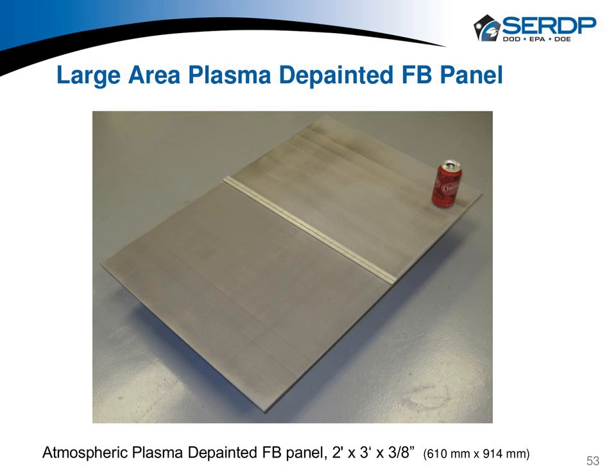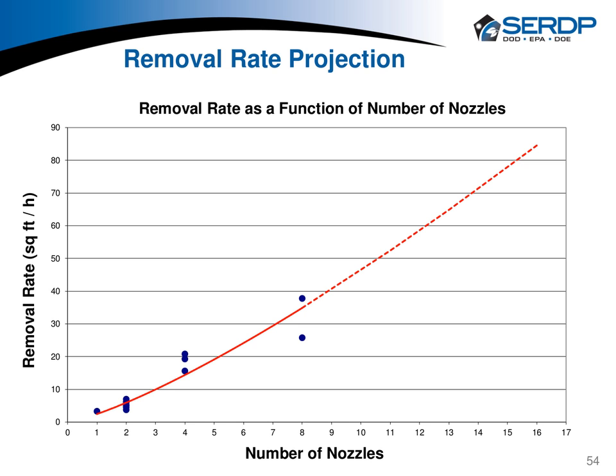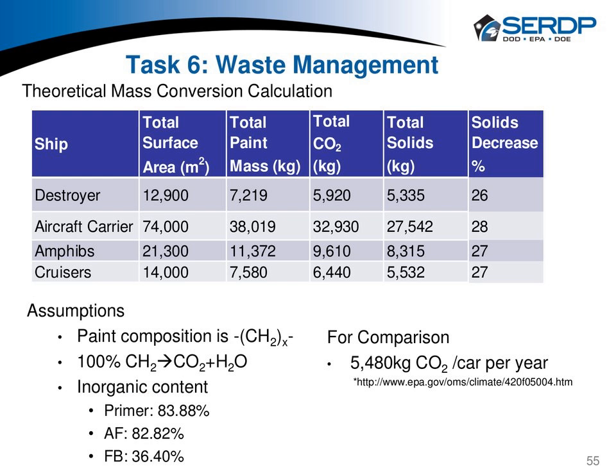Now, the next slide is a very simplistic summary of the trend that we observe, increasing the number of nozzles up to our targeted removal rate of 50 square feet an hour. So we were really close. We're right around 10, 11 nozzles to get us to where we needed for 50. But of course, this is just a very rough sketch, but it should give us an idea of scale up in the future. Just pick a number. How big do we want the system to get? It's very simple. You just gang them together and make as many as you want.